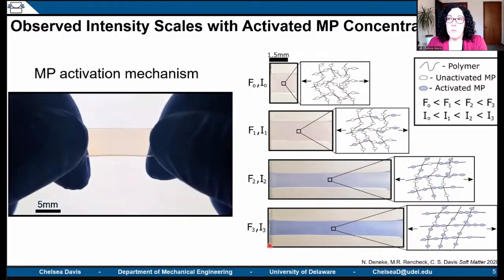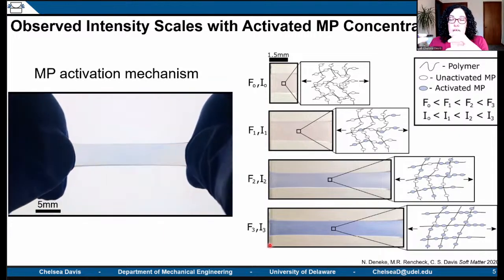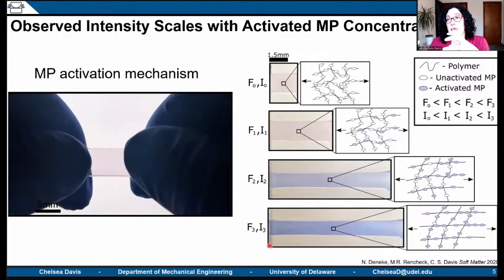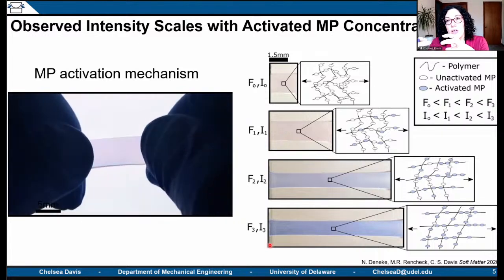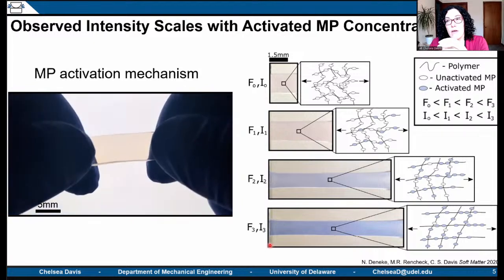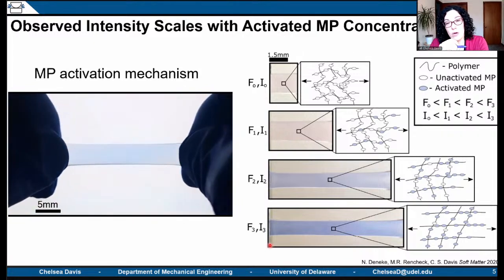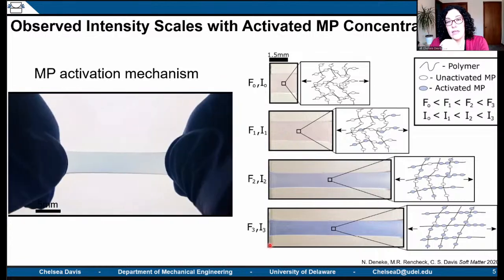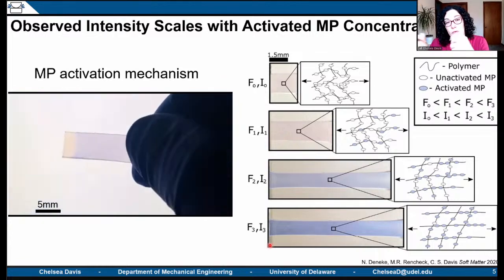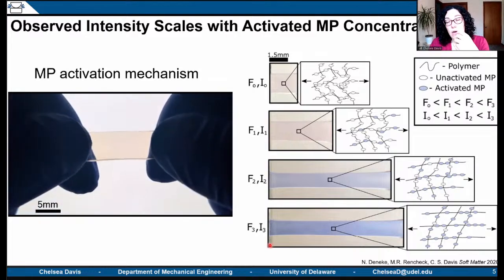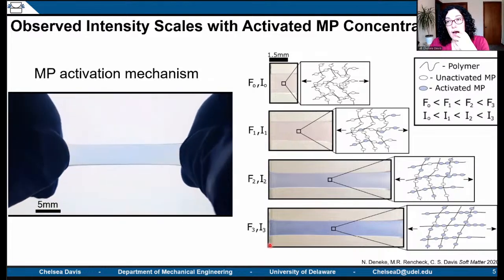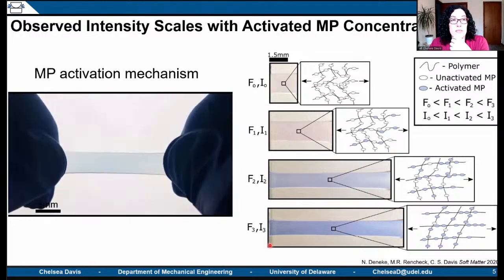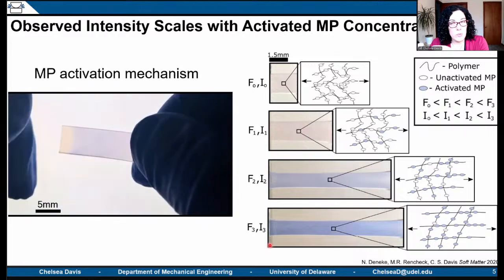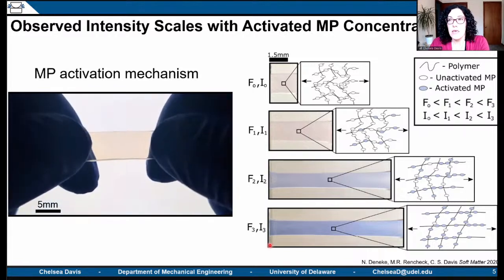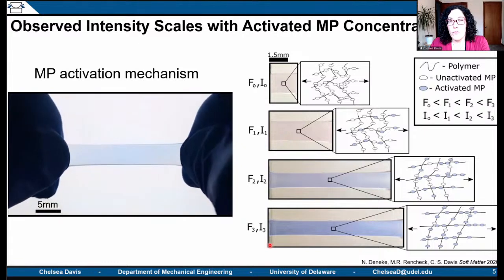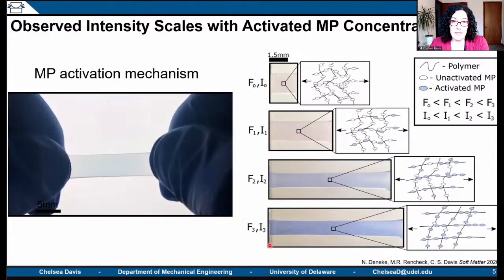before it reverts. So if you're looking at damage accumulation under fatigue or cyclic testing, you have to be really cognizant of the reversion rate of your mechanophore with time and relate that to the strain rate, or how quickly you are applying those cycles. I think there is potential there for using this to measure damage accumulation, which I recognize is not exactly fatigue. I think we could do it for fatigue. I don't know anything about synthesis with ball mills.